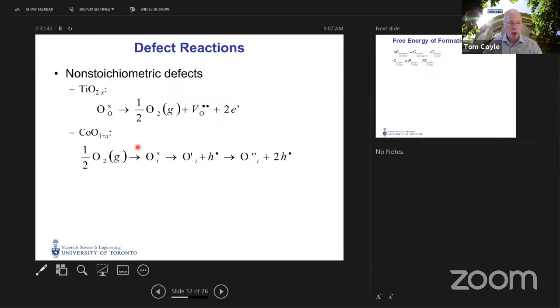We can have other types of reactions. For example, cobalt oxide, where again, cobalt can exist in multiple oxidation states. Cobalt oxide tends to become superstoichiometric in terms of oxygen. One way in which we can explain the addition of oxygen to that material is to take an oxygen from the atmosphere and put it on an interstitial site in the cobalt oxide lattice.